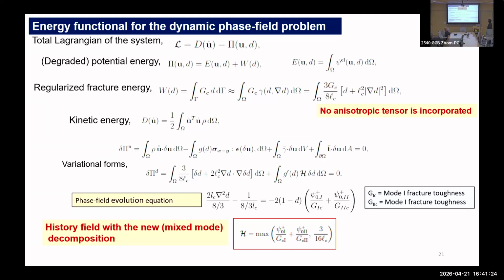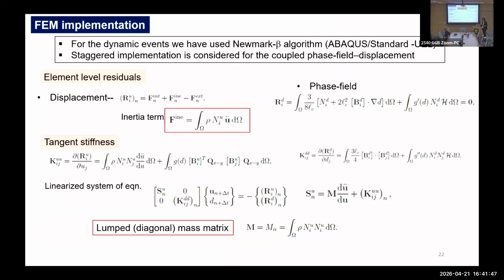And we have a new history function because now we have two parts of the free energy or the elastic energy, one for mode 1 and one for mode 2. They are individually compared with respect to the two modes of fracture toughness to get the driving energy. Okay, so these were the changes that were done in the phase field setting of the work. Then, of course, we implemented, and I did not mention this in the first part of the work, the numerical implementation still uses the Abaqus platform for the solver. So we write a user element routine, and for the dynamics, we have used a Newmark beta algorithm.